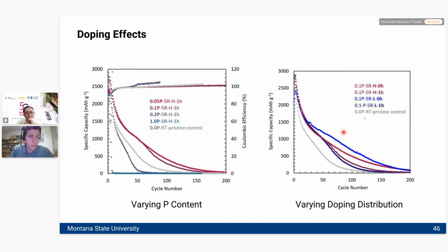Different temperatures and different soaking times in the presence of phosphorus give rise to different phosphorus distributions in the material. What we always found was that if you soak for a very short amount of time at a low temperature, in other words, preferring to put the phosphorus at the edges of the particles as opposed to homogeneously throughout the particles, you always had a better outcome. And so it was all about surface doping. You want to get phosphorus as close to the surface of the particles as possible in order to make the best effect, and you want to have a relatively low concentration of phosphorus.